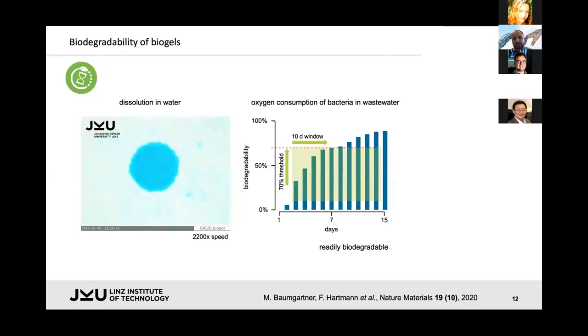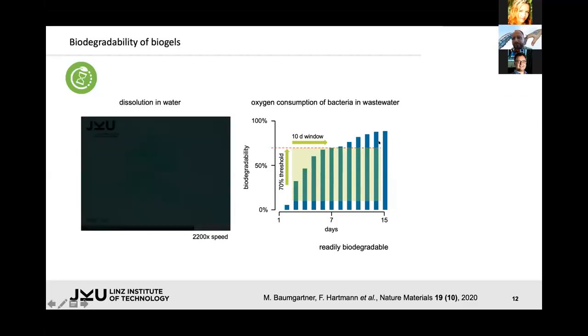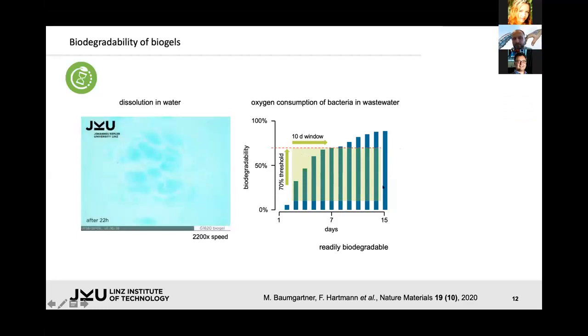What you really want is that the polymer chains are broken down. And for gelatin, that's relatively simple. That happens enzymatically, for example, through wastewater bacteria, and you can monitor their oxygen consumption over time, and then you can see that they're actually feeding on your material. And if you're hitting this 70% threshold in this specific test over 10 days, then by EU norms, the material is considered entirely biodegradable. So we had this part of the matter basically solved.